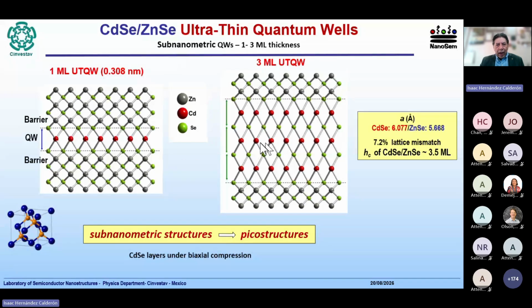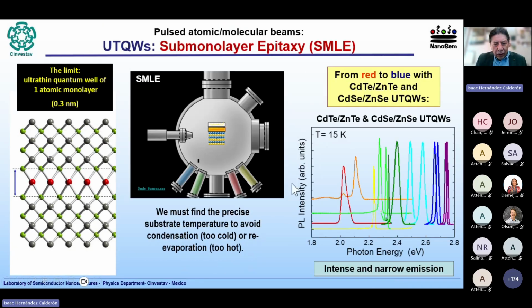structures. And the active material of the quantum wells is cadmium selenide, which is always in pseudomorphic growth under large biaxial compression. So the growth of these ultra-thin quantum wells is done in what we call a layer-by-layer mode. This is a schematic drawing of the chamber with a sample that is being grown. So we deposit layer by layer the atoms, the different types of atoms, cations and anions, in such a way that we can have control of thickness and composition of these ultra-thin quantum wells.